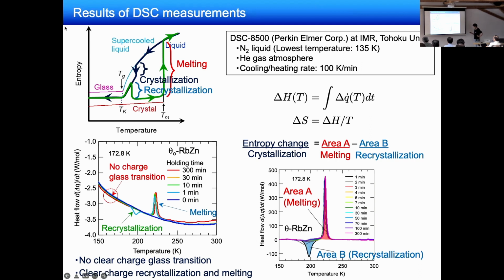So in this study, we cooled the sample down to a target temperature, and we kept the temperature of the sample during the crystallization, and then we cooled the sample down to a low temperature. And after that, we measured the DSC in the heating process. Okay, so this is an experimental result of the DSC measurement.